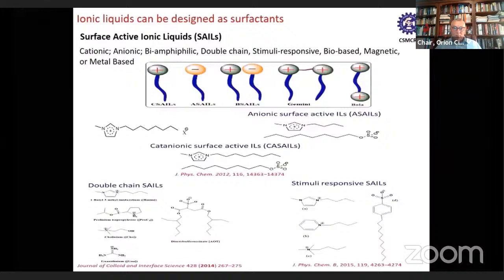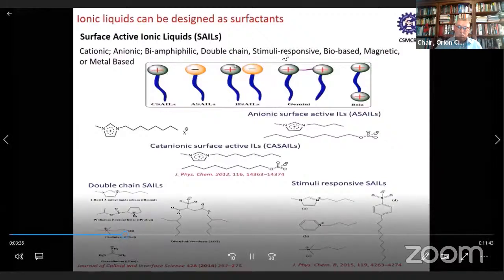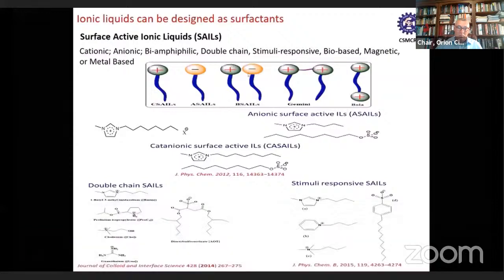If we look at the nature of surfactants, ionic liquids can also be designed as surfactants because they are tunable in nature, and we can make surface active ionic liquids just by incorporating amphiphilicity in constituent ions of the ionic liquids. So they can be cationic surfactants with a hydrophobic tail attached with the cation. Then they can be anionic surface active ionic liquids. One can make biamphiphilic ionic liquids, double chain ionic liquid surfactants, stimuli responsive, bio-based, magnetic, or metal-based. So different kinds of surface active ionic liquids can be synthesized depending upon the choice of cations and anions.